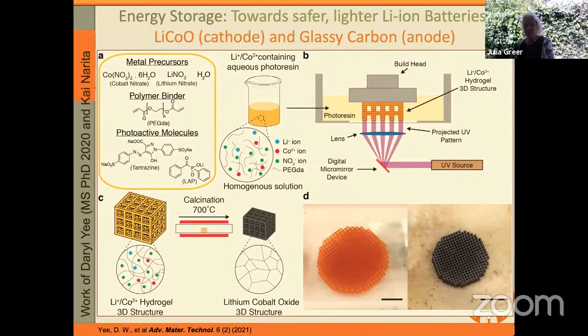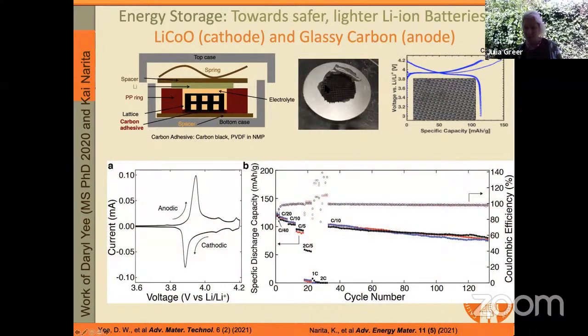Okay. I'd like to finish by going a little bit into the energy storage. So many people these days are working on lithium-ion batteries. And so using this kind of an approach that I just showed you, this hydrogel-based approach, we set out to make a complex oxide. So this is lithium cobalt oxide. And it's a typical material for cathode chemistry in a variety of different batteries. And so what we fabricated is a carbon-based anode and an LCO, or lithium cobalt oxide based cathode. And so when you put them together, so here's the carbon anode, it's all fully architected.